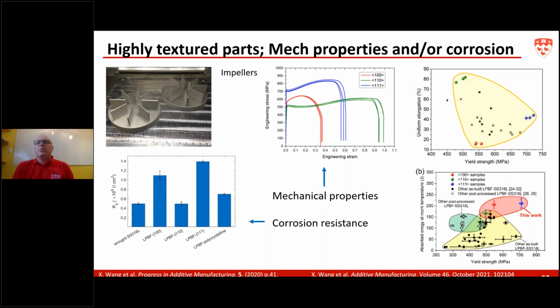The next slide, please. This is something that is fairly rare. Only a few people in the world are working on this. With the 3D printing process, there's a possibility of texturing the microstructure. So you have an example here on impellers for pumps. Depending on how you align the atoms during solidification, you can texture the part with what we call in the jargon the 100, 110, and 111 orientation. And you can see on the right side of this slide the different mechanical response that you have depending on the orientation. So you can now start thinking, at a fairly low cost, of fabricating components that have a high texture and can give you specific properties that conventional material cannot give you.